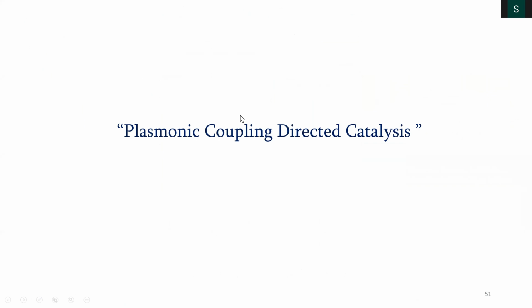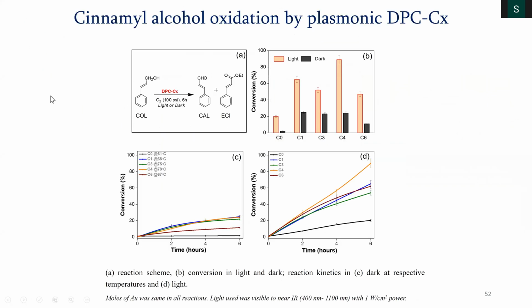So we took the C4 and did some catalysis. This is a simple catalysis where alcohol oxidizes to aldehyde, and there is a side reaction of forming the ester. So if alcohol to aldehyde, you see the conversion. Take C4. In dark, it is around 20%. In light, it is around 90%.